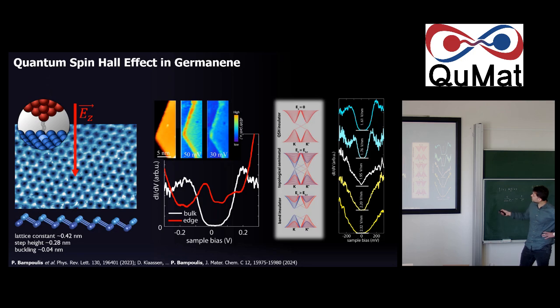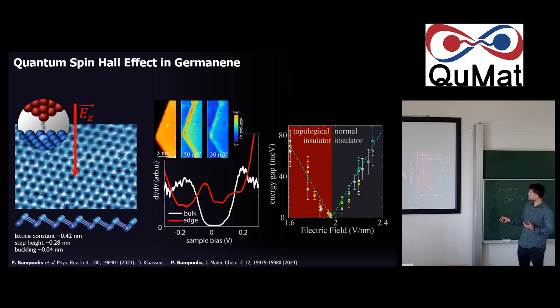So we did this. We tried to repeat the expectations from the theory experimentally, and we saw that indeed, if you measure the band gap and you simply bring the tip closer and closer to the surface, the strength of the electric field builds up, it gets stronger, and you see that the band gap slowly closes. You get this V-shaped character against the dI/dV, which is reminiscent of a Dirac cone or a semi-metal. And then after that point, you keep increasing your electric field, and you'll be opening a band gap. We can do that reproducibly, also between different layers, different samples and so on.